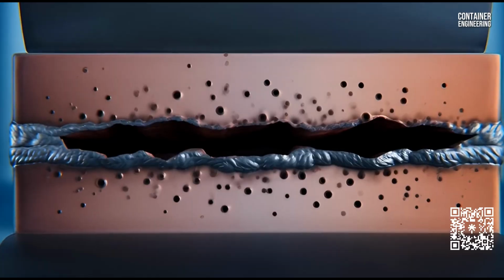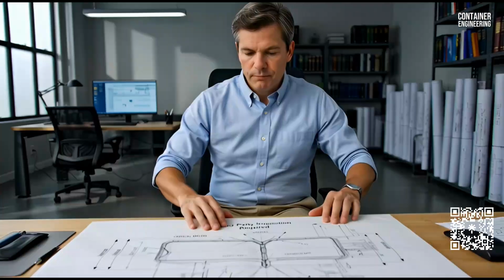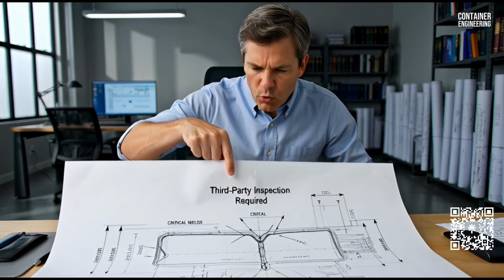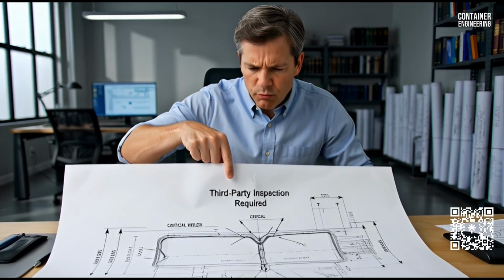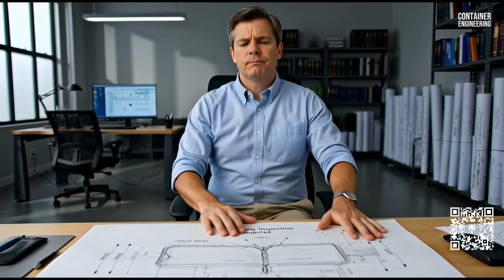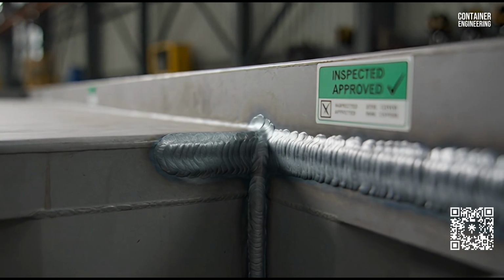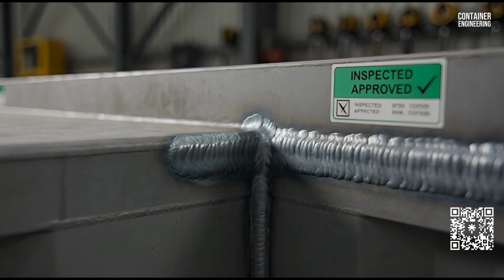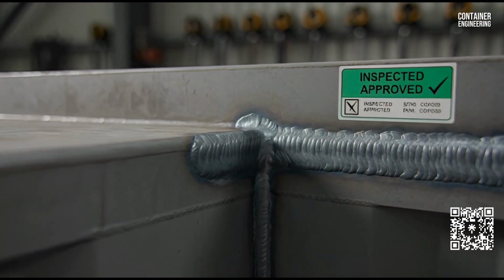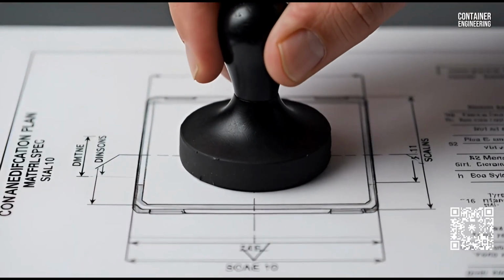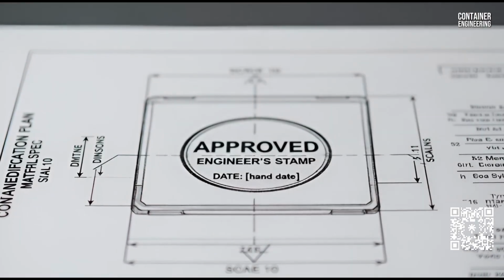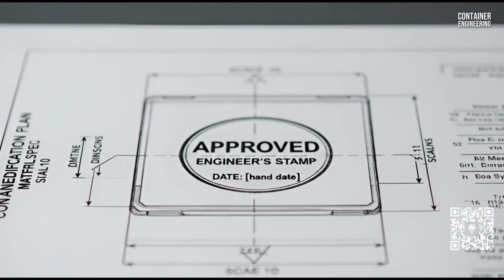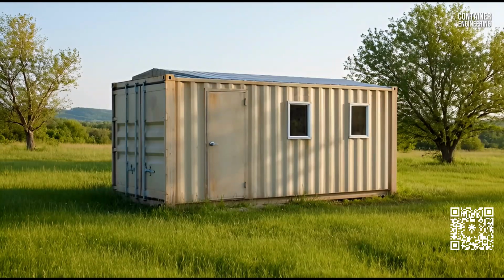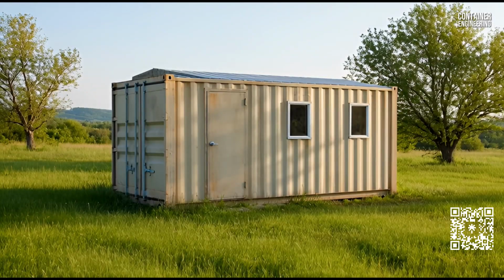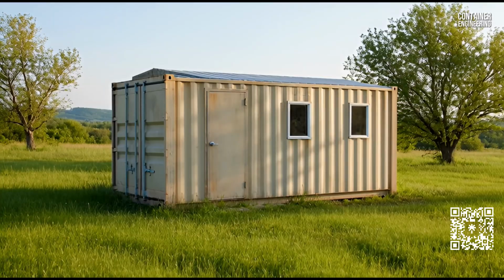I inspected a container home in coastal Georgia that had been occupied for 4 years. The owner had spray foamed the interior directly against the steel with no vapor barrier. Condensation formed between the foam and the steel. When we removed a section of foam for inspection, we found corrosion had reduced the wall thickness from 1.5 millimeters to 0.9 millimeters. 40% loss of material. The corrugations were flaking apart in my hands.